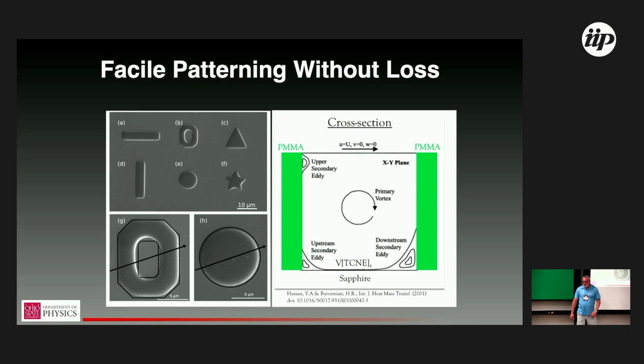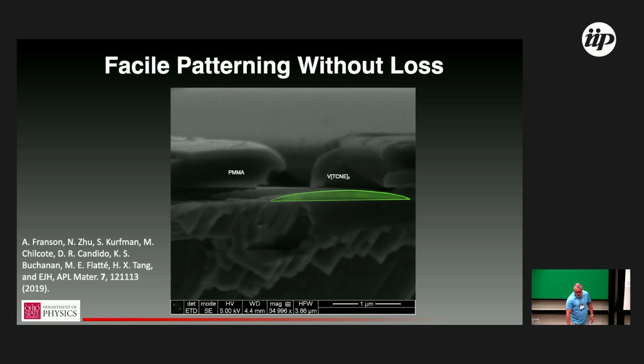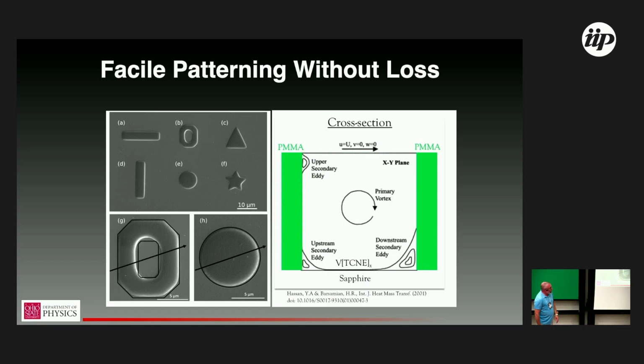And so coming back to this trench, if you imagine gas flowing across this, the gas needs to flow down into the trench and out again in order to bring the precursors into play. And here this diagram shows flow perpendicular to the trench, but similar things happen if you're flowing parallel to the trench: you develop these eddies in the corners. So you develop a vortex where the diameter of the vortex is roughly the depth of your PMMA. In this case, where it's basically a 1-to-1 ratio, you have one big vortex in the middle,